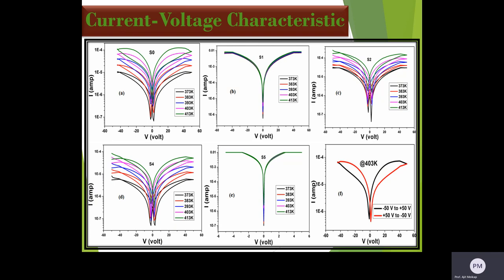In this state, a local conducting path of low resistivity may be generated. Now, for decreasing voltage from 50 to 0, current suddenly drops and does not follow the same path. At this time, some dipoles are trying to back in its initial state, then free charge carriers are maybe trapped inside the grain and the grain boundary, which decrease the value of the current.